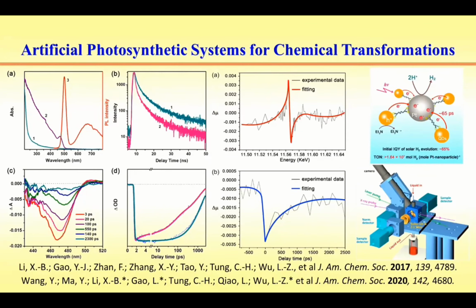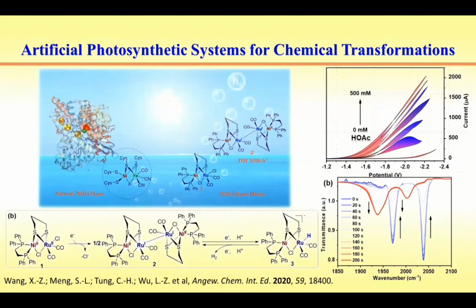On the other hand, is it true that the active site accepts the electrons from the photosensitizer? In this case, we provide the first example of using the time-resolved absorption spectrum to give a picture of the reduced active site's spectroscopic signal. The time scale for this reduced signal is in the 60 picosecond range. That means the photo-induced electron transfer from the photosensitizer to the active site takes place.